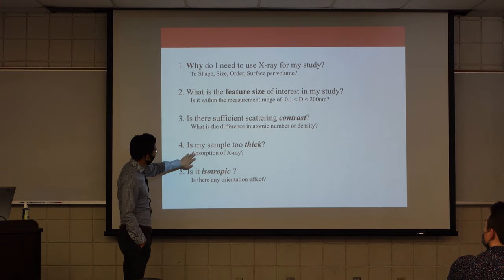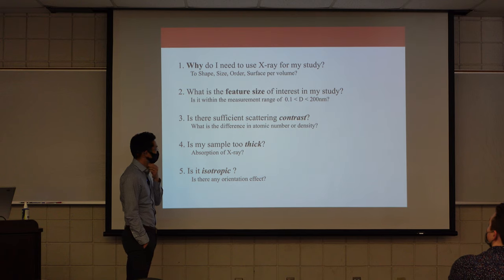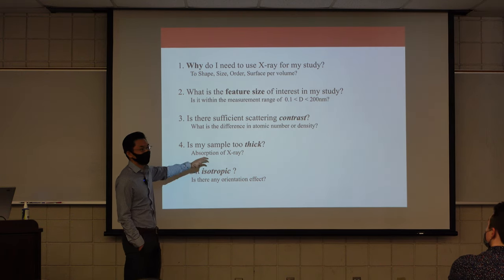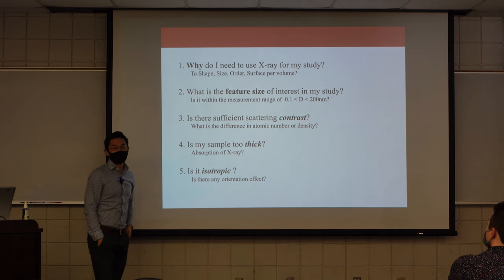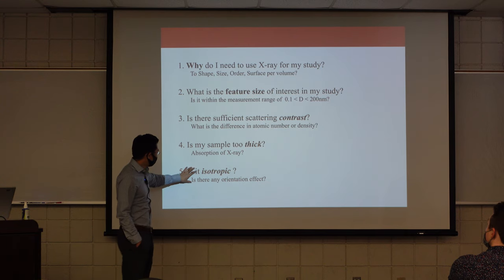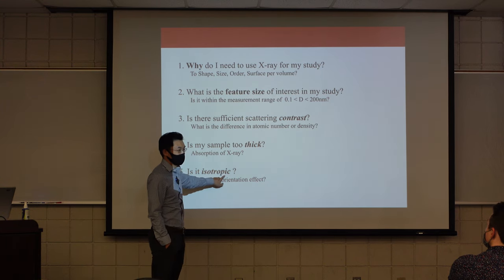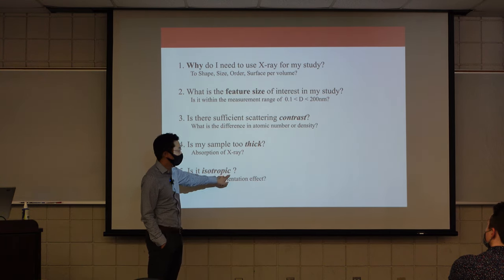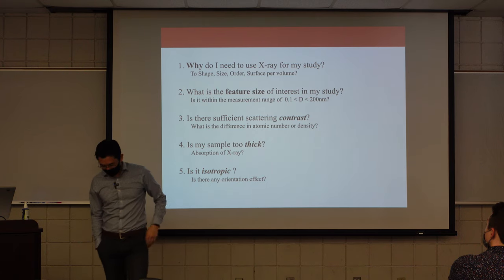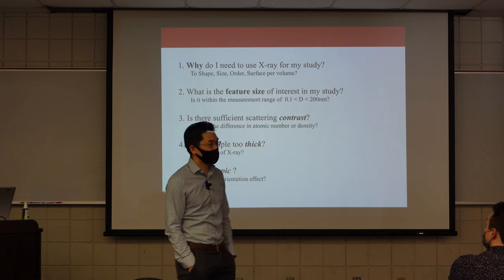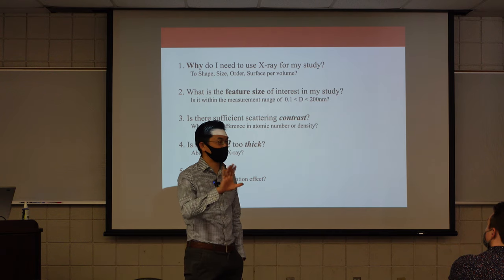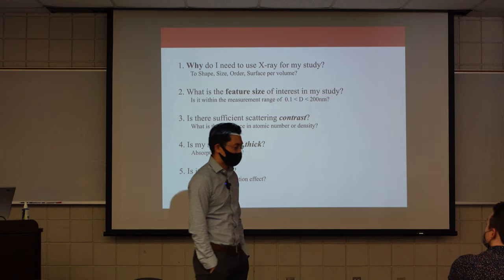Four, is my sample too thick or too thin? That's a good question. We talked about attenuation. You need to ensure you get reasonable transmission to get good results. Last but not least, is it isotropic? It is an interesting question, because if your sample is anisotropic, then you need to consider how to mount your sample with respect to the X-ray. You need to rotate the sample to get all the information out.